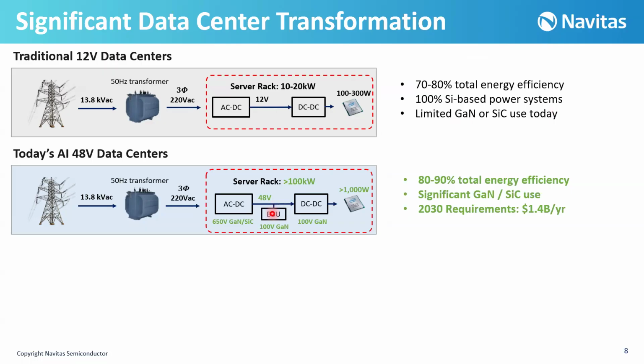By the way, I was saying that in the second stage, we are stepping down this voltage to 48 volts, and by increasing this voltage from 12 volts, obviously we are lowering the current flow, and we are reducing the power loss. And then we are converting DC-DC and powering the components with more than 1,000 watts. The power density of this server rack is more than 100 kilowatt. In this architecture, we are using 650 volt gallium nitride and silicon carbide in the AC-DC converter, 100 volt GaN in the BBU battery backup, and also 100 volt GaN in the DC-DC converter. Thanks to significant usage of gallium nitride and silicon carbide, we can now increase the total energy efficiency from 70 to 80% to 80 to 90%. And the market requirement by 2030 is 1.4 billion per year.